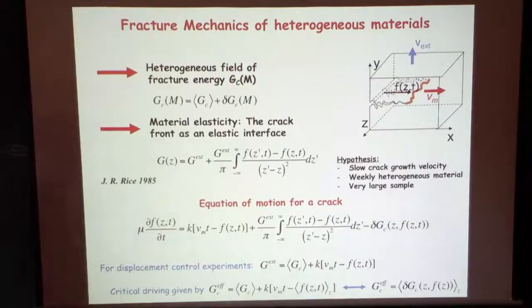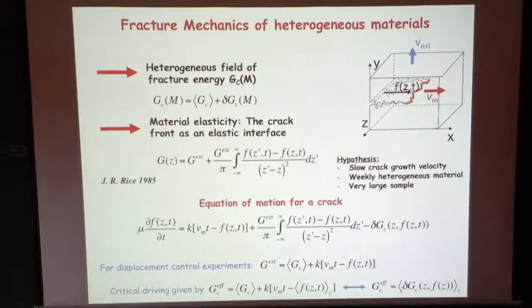Have you measured some sort of dynamical exponent? Because you were talking about time series, maybe there are correlations between events, like we talked about last week with earthquakes. With the depinning model, there's really no correlation. Okay, people have measured Omori's law in fracture. They have measured correlation in avalanches at a very short time scale, millisecond, and it's right now not so clear if we are talking about this type of effect where one avalanche can be composed of several avalanches. If we have viscoelastic effects of the type discussed by Alberto last week, it's an open question.